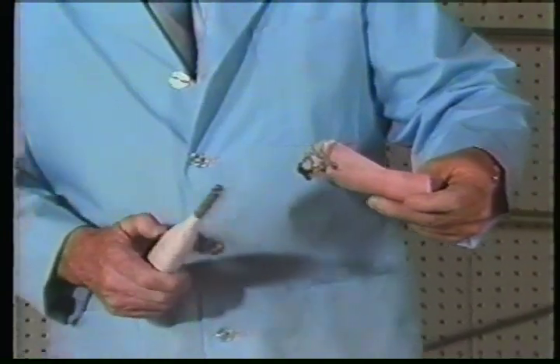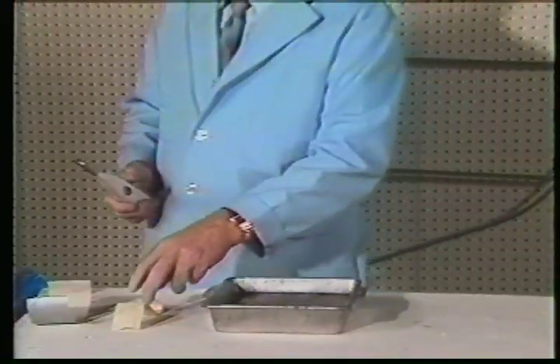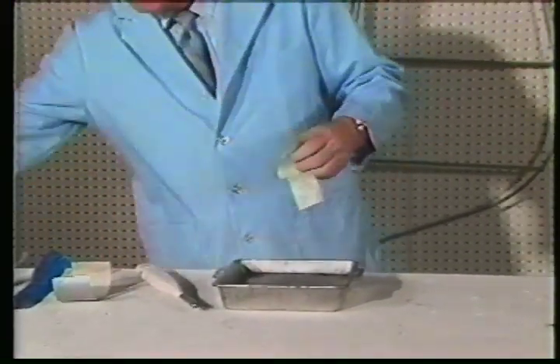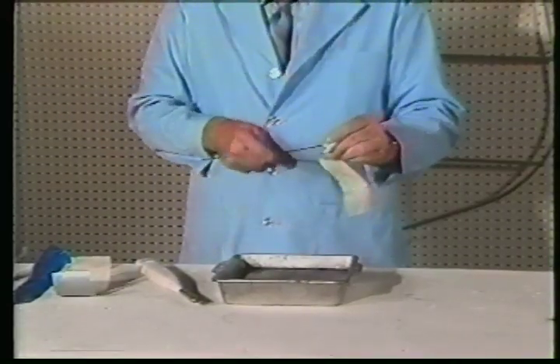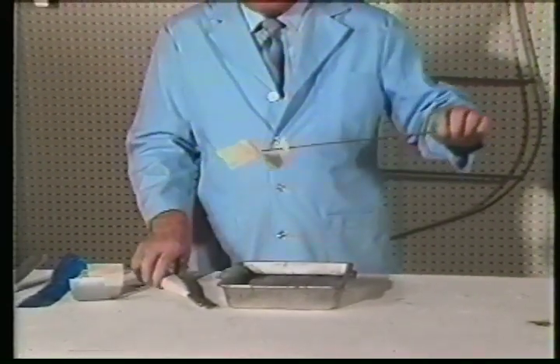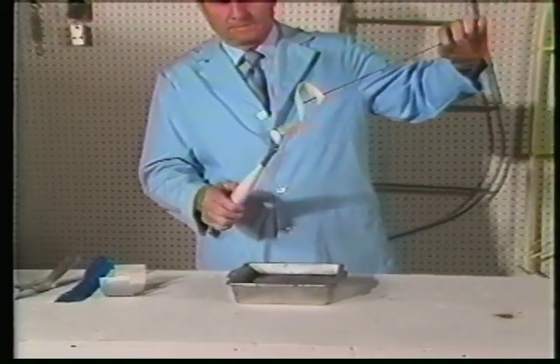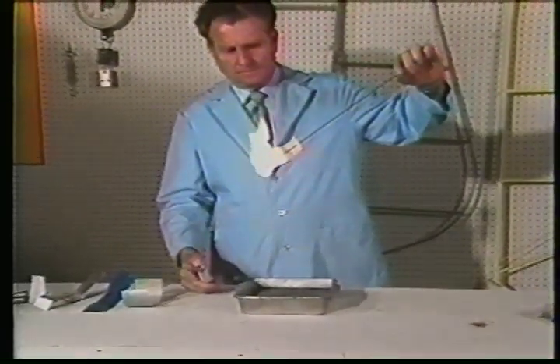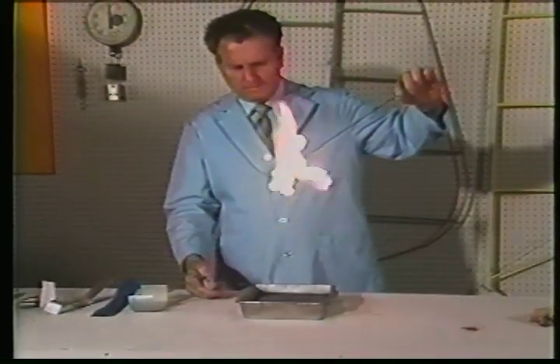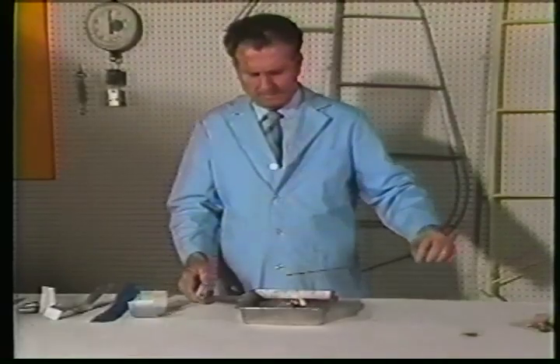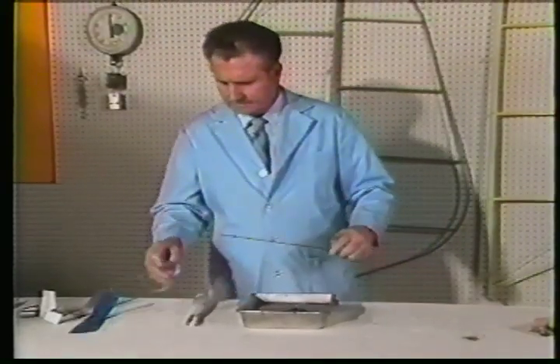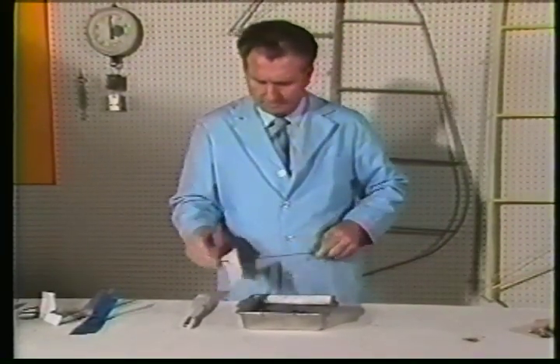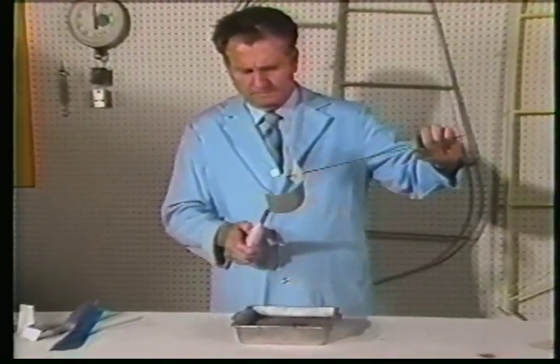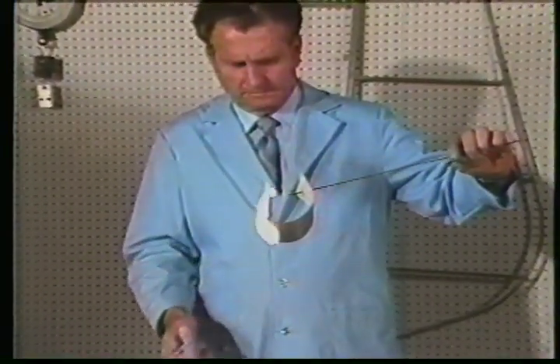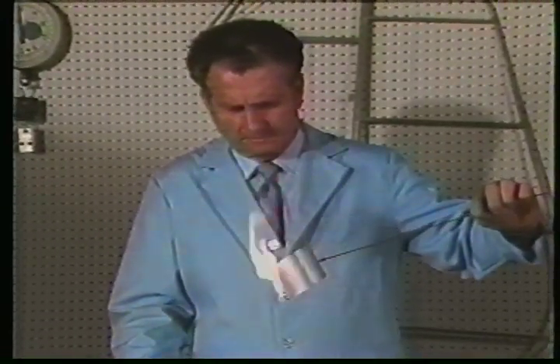For the enlightenment of those who were not familiar with the fast-burning characteristics of cellulose coatings, we will test a few samples on different types of fabric. This first sample is clear nitrate dope on polyester, and it burns rapidly. Next is cotton fabric coated with nitrate dope through an aluminum pigmented nitrate dope finish, and it also burns rapidly and with a noticeable sparkle effect due to the aluminum pigments.